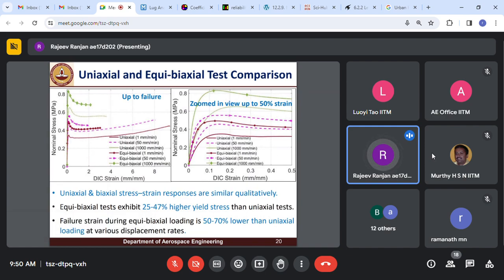In order to see the effect of stress field, uniaxial and equibiaxial test responses have been compared. This plot shows the stress and strain response up to failure for both uniaxial and biaxial loading, and this is the zoomed-in view of this plot up to 50% strain. We observe that the uniaxial and biaxial stress-strain responses are similar qualitatively. However, quantitatively they vary a lot. During equibiaxial testing, the yield stress was 25 to 47% higher as compared to the uniaxial test.